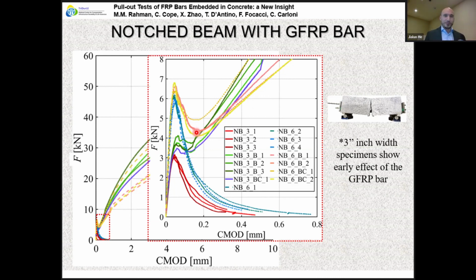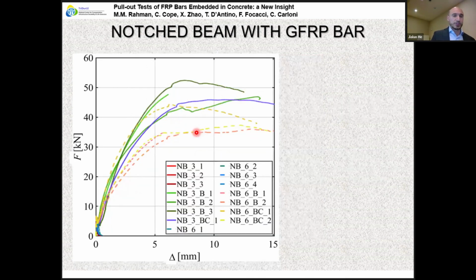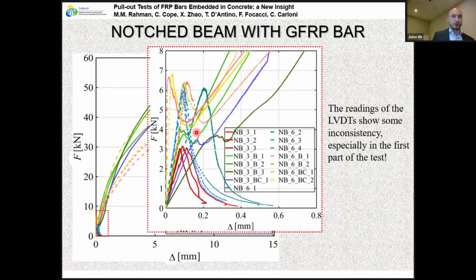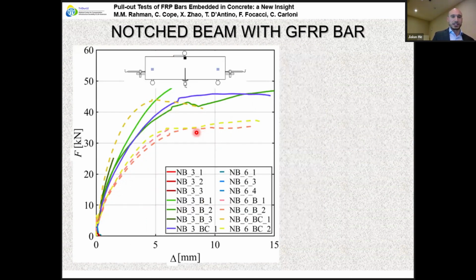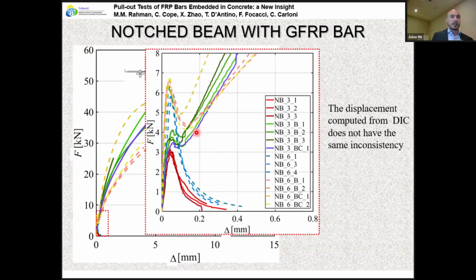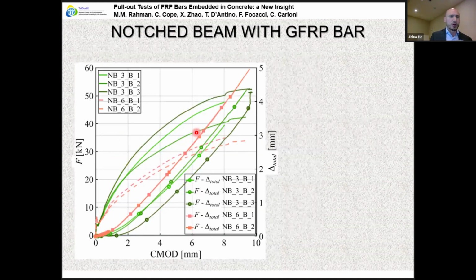So basically, the picking up of the load from the bar depends on the width of the beam. These are the responses in terms of load versus vertical displacement. They're not as nice as the load versus the CMOD, the opening of the crack. So we look at the same load responses using DIC, and if you use DIC, you actually have a nice response. The reason being that, sometimes in small displacement, the sensors are not that accurate and are very sensitive to any out of plane displacement. We also look at the displacement at the free end.